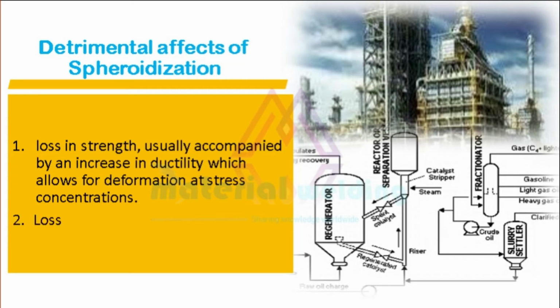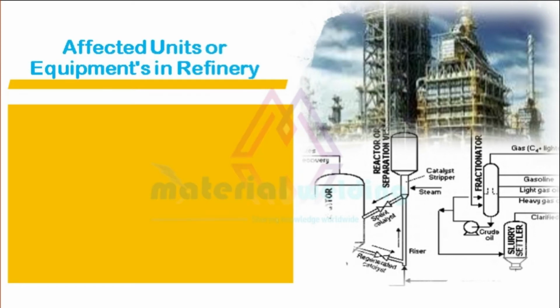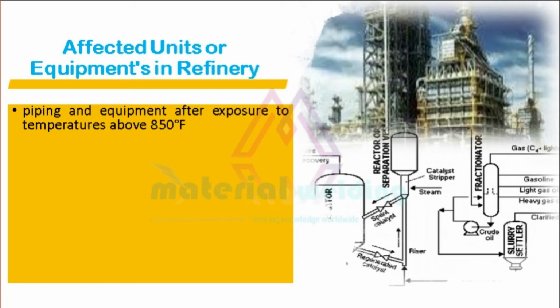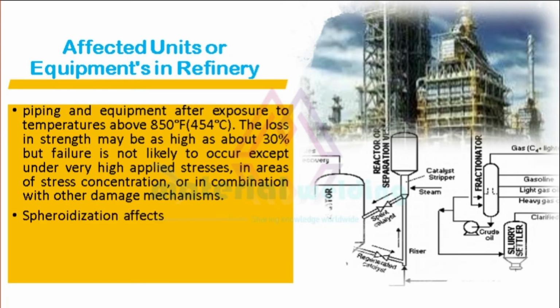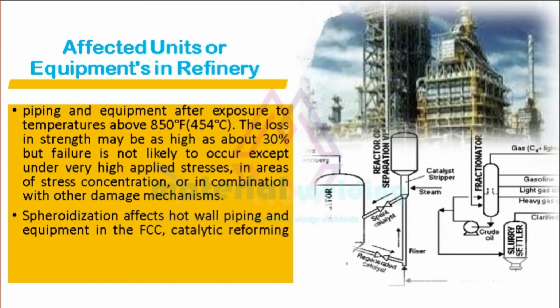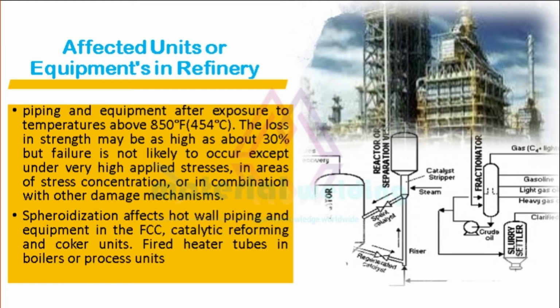Affected units or equipment in refinery. Piping and equipment after exposure to temperatures above 850 degrees Fahrenheit or 454 degrees Celsius. The loss in strength may be as high as about 30%, but failure is not likely to occur except under very high applied stresses, in areas of stress concentration, or in combination with other damage mechanisms. Spheroidization affects hot wall piping and equipment in the FCC, catalytic reforming and coker units. Fired heater tubes in boilers or process units may be affected.